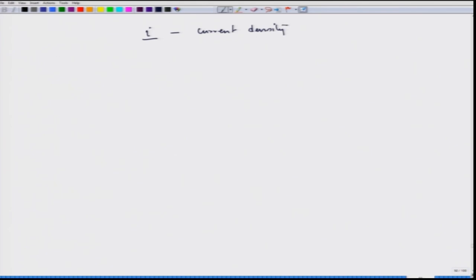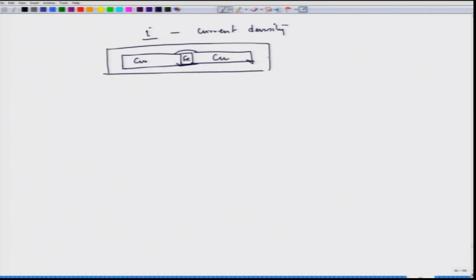If we recall, we saw that in case of galvanic corrosion, if we have a copper plate, this is a copper plate, and if we have an iron rivet which is connecting these two copper plates, and we put it in NaCl solution, then according to galvanic corrosion, this one will dissolve quickly, and finally the rivet would lose its joint strength. So, this is the example we put in while discussing galvanic corrosion.